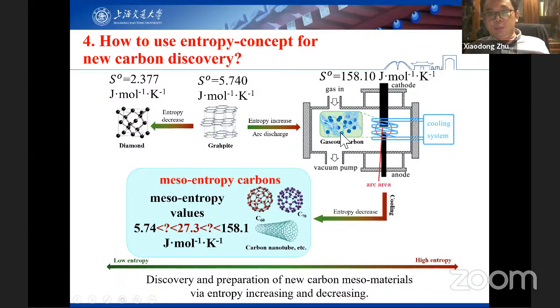And everyone knows how we fabricate fullerene. We have the graphite electrode here. After the arc, we can produce carbon gas. The entropy for the carbon gas is more than 150, so it's a high entropy species. After that, we can get the fullerene, and the carbon nanotube. What is the value for the fullerene? It's 27. So we can see the value for the fullerene locates between graphite and the carbon gas. Still, we can find the carbon nanotube locates between these numbers. From the thermodynamic entropy, we can find the relationship of these carbon species.